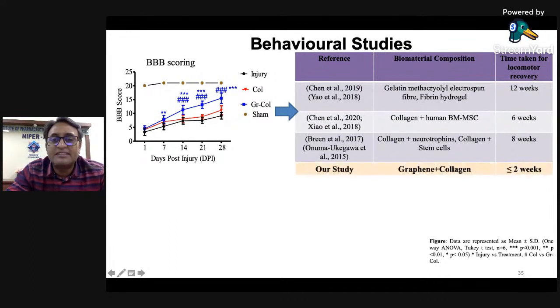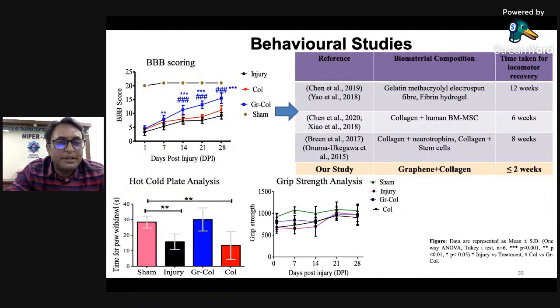We further tested the material with grip strength analysis and hot-cold plate analysis. There was not much difference in grip strength; it was all the same, since these kinds of tests are sometimes notorious and don't give clear data. We did hot-cold plate analysis, measuring paw withdrawal upon temperature change, and found they had recovered their sensory motor activities. The Gr-Col group almost achieved similar properties or activities to sham, while the injury and collagen areas did not show much difference.